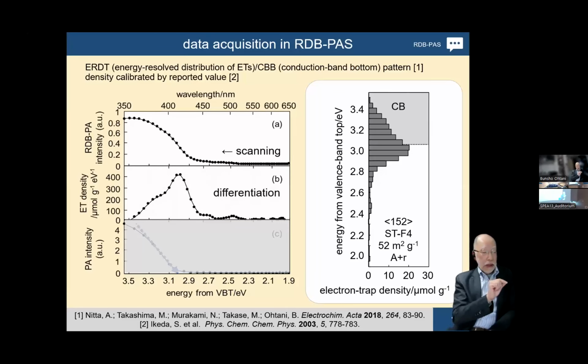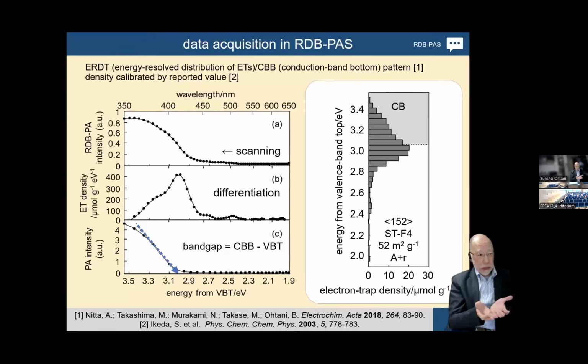The conversion coefficient is calculated from another photochemical method. This is converted into the absolute density of electron traps. And then, using only one modulated light beam, an ordinary PA spectrum, it is possible to get a diffuse reflectance spectrum-like spectrum.